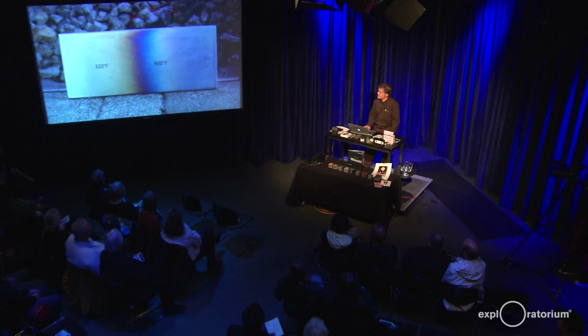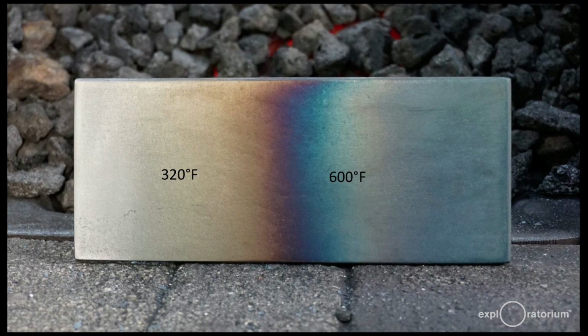Not entirely safe. Now, the really wonderful thing about tempering for the blacksmith is that the entire range of useful tempering temperatures can be displayed as temper colors on the surface of the steel if it's polished before the tempering takes place.